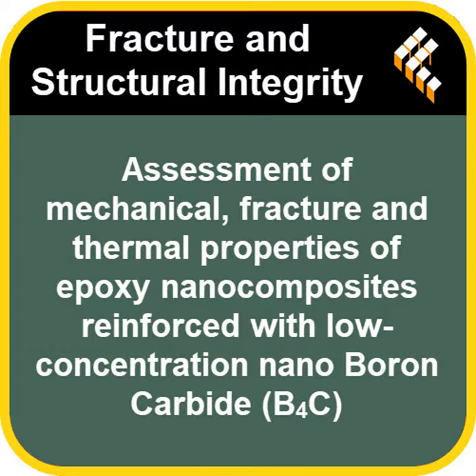And does that improved toughness show up in impact tests too, like how it handles a sudden hit? It does. The impact strength, measured by the Izod test, also showed a big jump. It peaked at the 0.4% concentration again, with a 62% improvement compared to the plain epoxy. Much better at taking a hit. And then there's flexural strength, how it performs under bending. This is another interesting contrast. Unlike tensile strength, the flexural strength also kept increasing progressively all the way up to 0.4 weight%, peaking there with about a 49% improvement. Okay, wait.